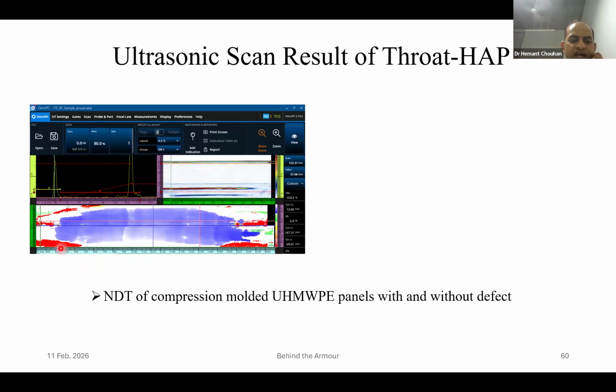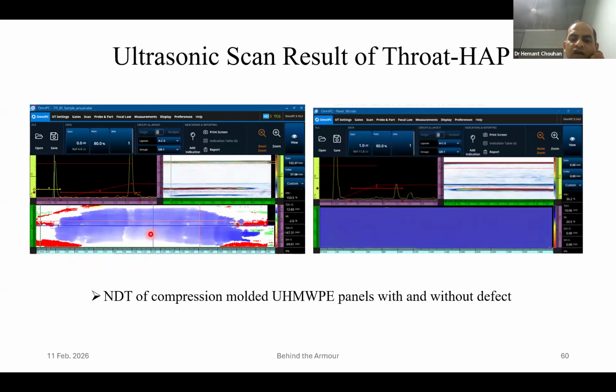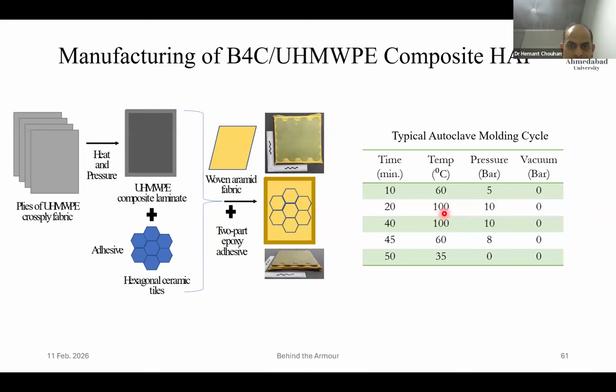And you can see a lot of reds and loosely white or less blue kind of spacing, whereas in this case, this is a perfect one. So this panel is a perfect one, and this one has got so many. Since it is not densely packed, it's a defective piece, and the bullet will perforate, let's say, these 100 layers. In this case, at least from the result of NDT, we can say that most probably this is supposed to stop the bullet.